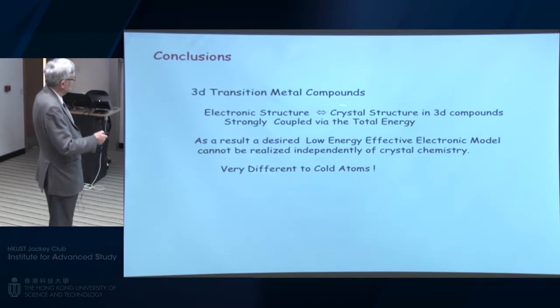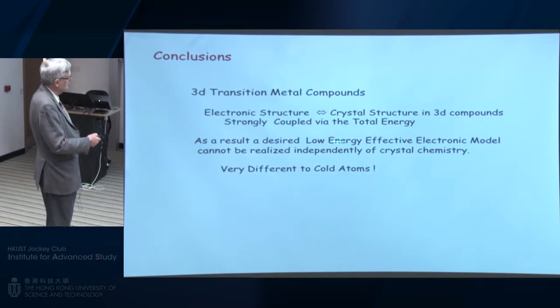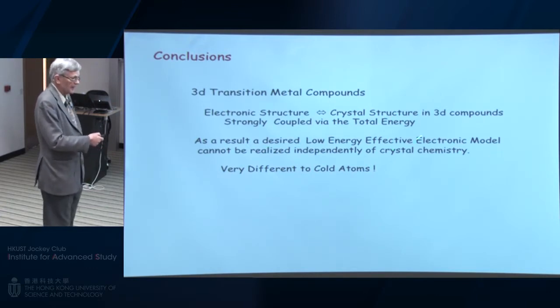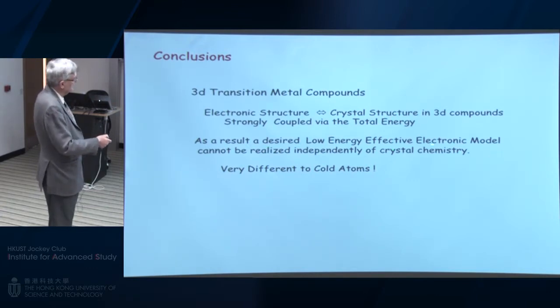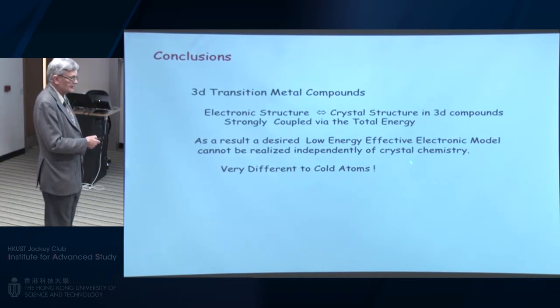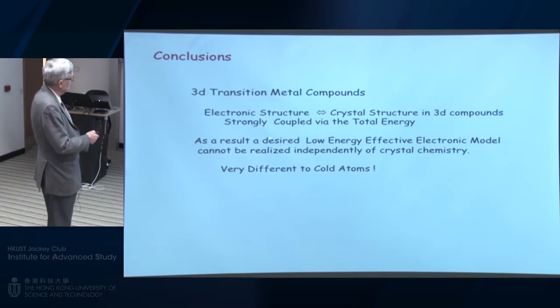These two are not independent. They're strongly coupled: you minimize the total energy by adjusting this with this. And so you cannot simply say, I'm going to have a nice Hubbard band with a nice symmetric lattice. This low energy effective electronic model that you're going to get cannot be realized independently of the crystal chemistry. It's the crystal chemistry which determines the nature of this low energy structure.